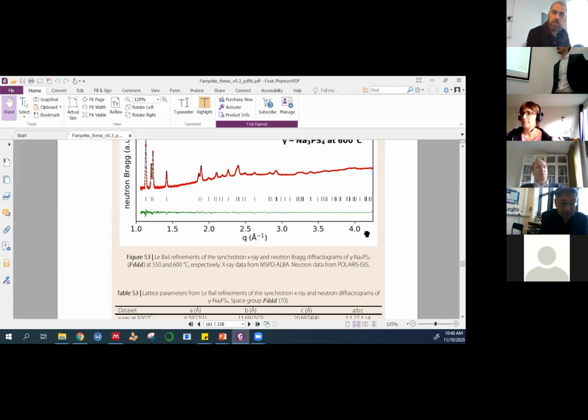No, I'm just facilitating. The interesting aspect of your structure is the difference between local and global order, right? That's the whole point, and that's immediately the challenge in your refinement. So you can lower the symmetry, and of course, if your lattice parameters remain the same, then that still obeys the reflections of a higher symmetry, but in terms of the ADPs, it allows you to break the local symmetry, if you see what I mean. I see the point. Yeah. So basically you're proposing we do something similar to what we did on the PDF of the alpha and the beta phase, basically trying to get something that appears to be more symmetric. No, I did not perform such a thing. Okay, I was just curious. I'm not saying it will work, but I was curious whether this is an approach you considered.